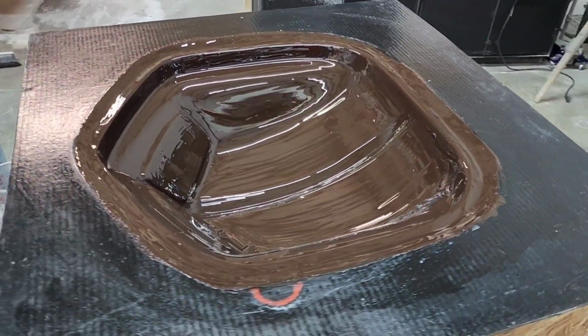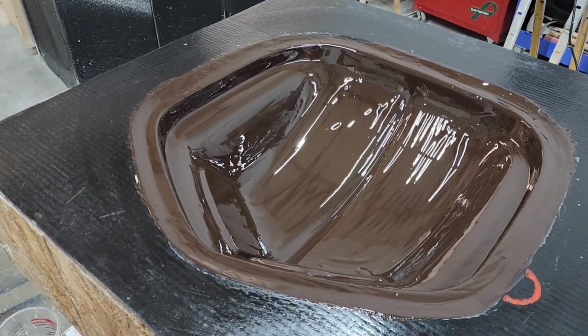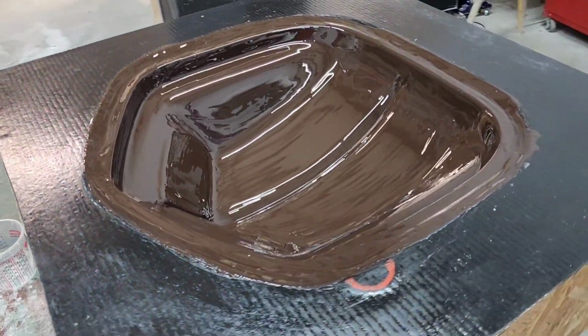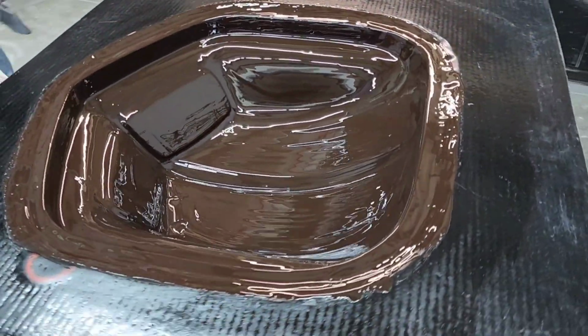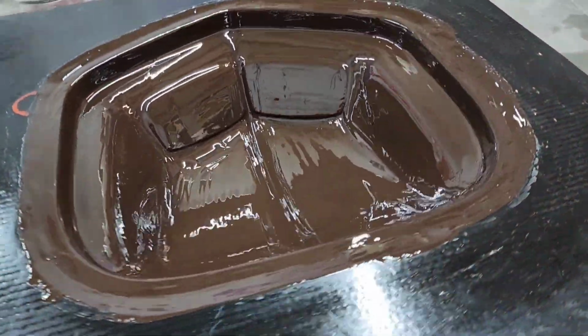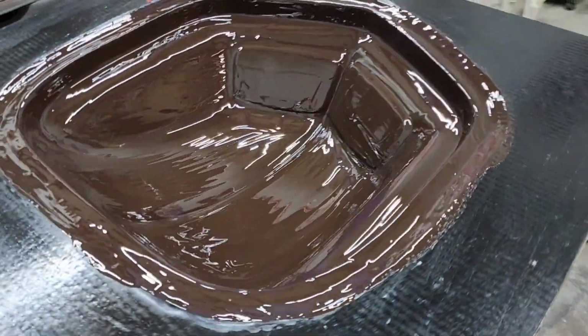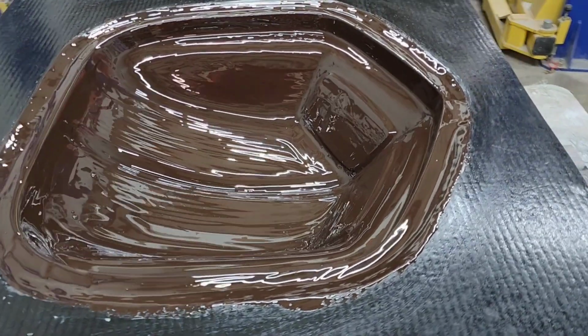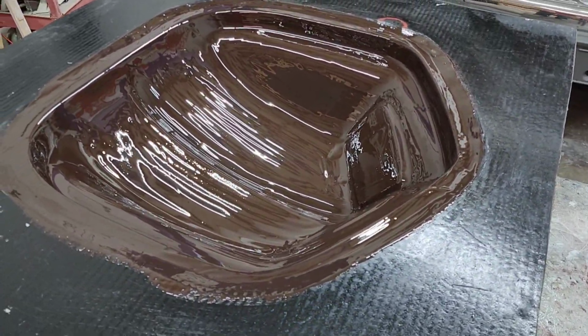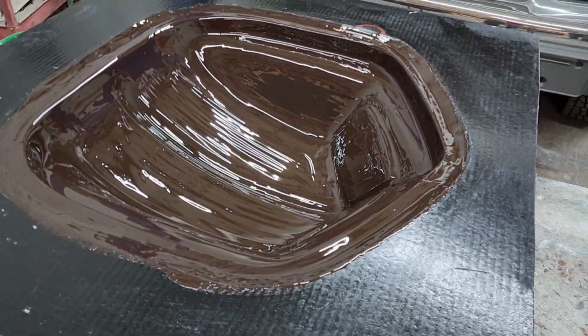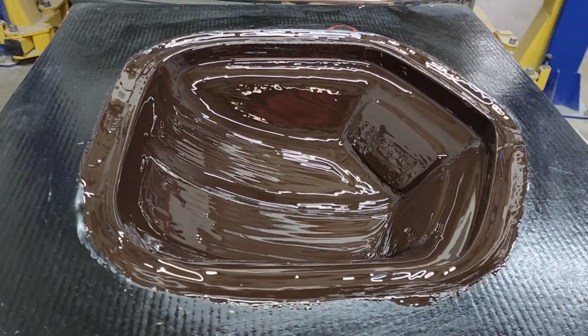Okay, so Brandon is finished laying it in. We just finished, so this is going to take another minute or two for all the brush marks and stuff to settle out. But this is what you want, a nice consistent brushed pattern all the way around, no thick spots. The thick spots can cause you problems in the future, and what I mean by that is the gel coat can cure at different times.